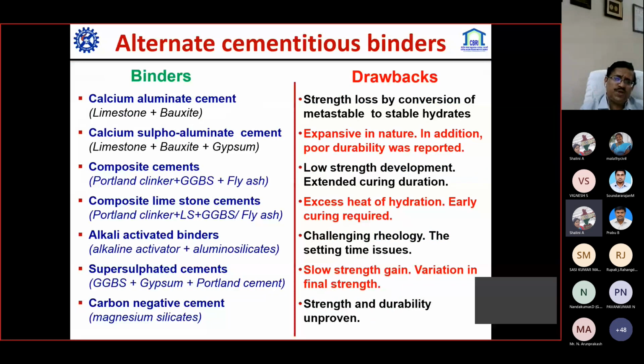People are working on that. A few binders have been tried, such as calcium aluminate cement, where they have added crushed limestone and bauxite, and the work is going on and they have found it okay. Somewhat there is a strength loss by conversion of the metastable hydrate, but overall there is no problem in functionality. Calcium sulfoaluminate cement uses limestone, bauxite, and gypsum. This is a little bit expansive in nature. It expands. In addition, some people have reported on durability, but work is going on.